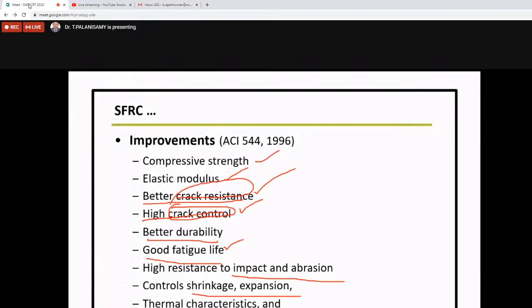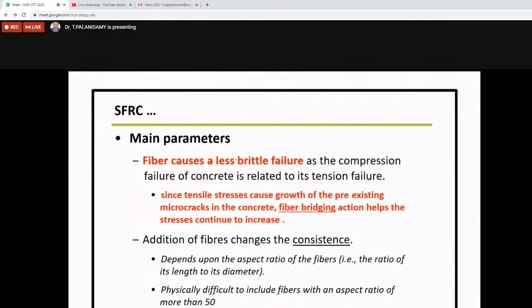If you add the fiber inside this concrete, what will happen? How about the debonding between the fiber and the concrete, and the reinforcement and the fiber? These kinds of things may be studied. These are some research areas. Then, main parameters. The fiber causes a less brittle failure as the compression failure of concrete is related to its tension failure. Since tensile stresses cause growth of pre-existing micro cracks in the concrete, the fiber bridging action helps the stresses continue to increase. So we want to see the fiber bridging mechanisms in detail. These improve the behavior of the structures.